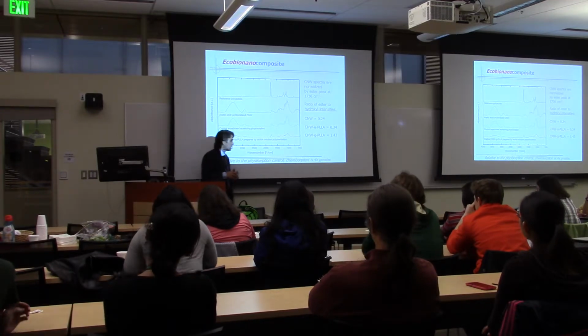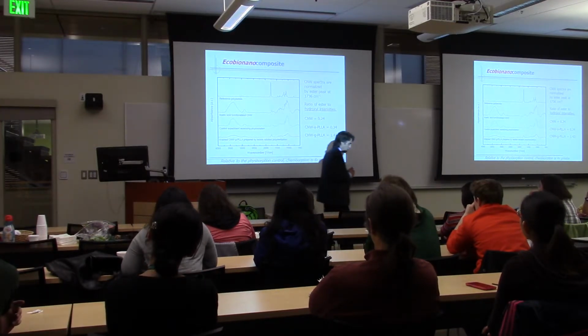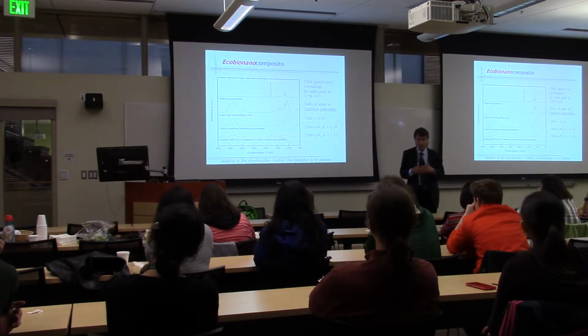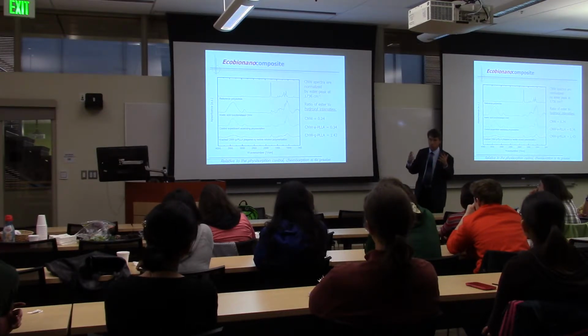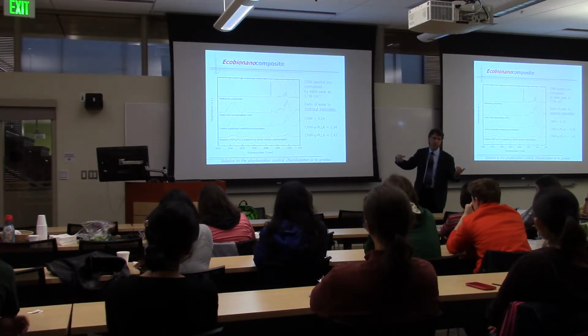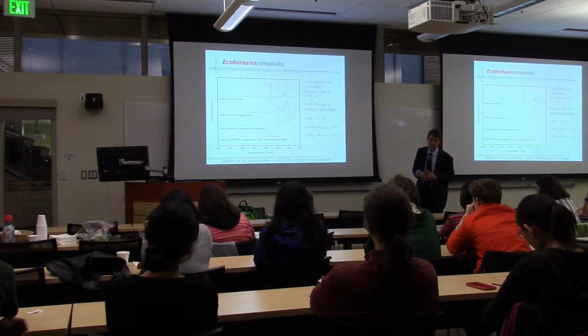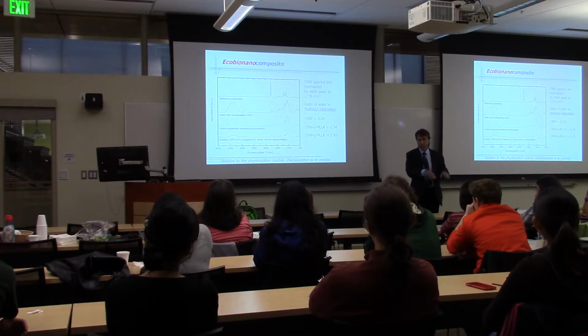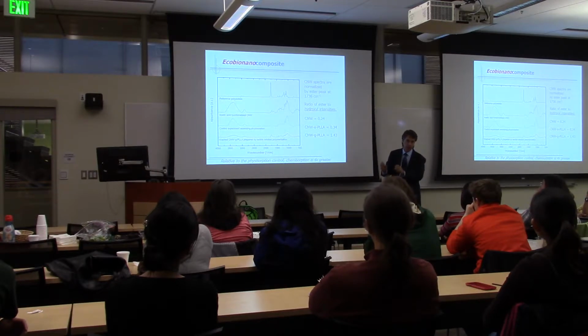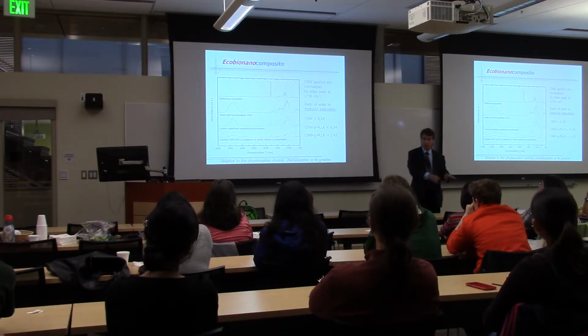Here is, again, the infrared spectroscopy. And I'm a big stickler with the students for doing control experiments, right? In this particular case, you really have to worry about, have you successfully attached the chains to the cellulosic nanowhisker, okay? Because if you just say, oh, here's FTIR, and I see both acetate groups and ester groups, so they must be attached. No. If you remember from things like your catalysis courses, we make a distinction between physisorption and chemisorption, right? What we're trying to accomplish is chemisorption, where it's actually covalently bonded to the surface. But of course, physisorption takes place as well.